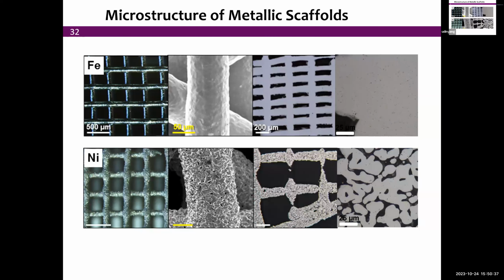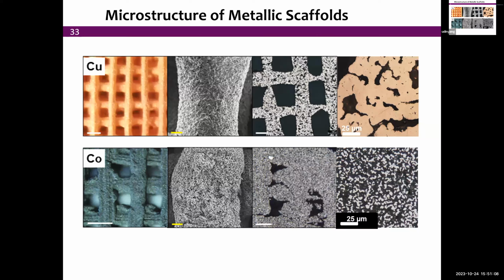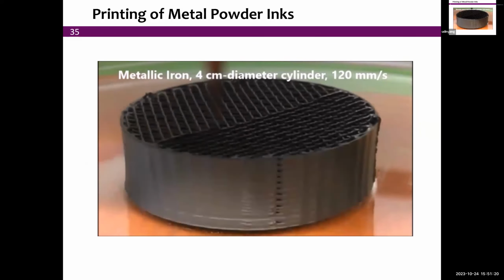And the difference between the two is really the packing of the particles as you print. If they're sufficiently close to each other, then everything sinters together. But if there's a lot of extra material, in particular if you have some binder that is burned out, you may end up with those meandering, open porosity structures. So you also have another ability to change the internal porosity of the struts, beyond, of course, the printed channels, that is the macro porosity in the material. Other examples are copper and cobalt here, an extreme case of on-purpose under-sintering. We get extremely high porosity. It's still strong and continuous in 3D, but you get really, really high surface area as a result.